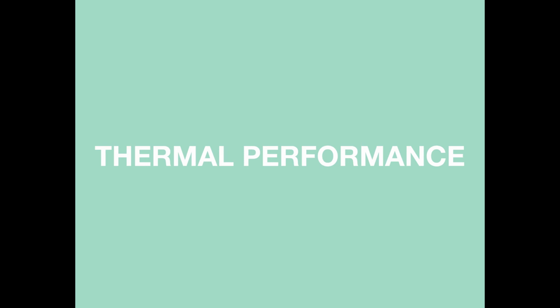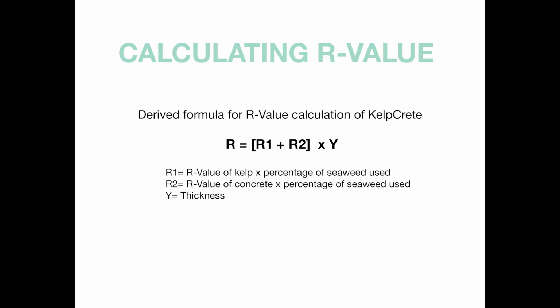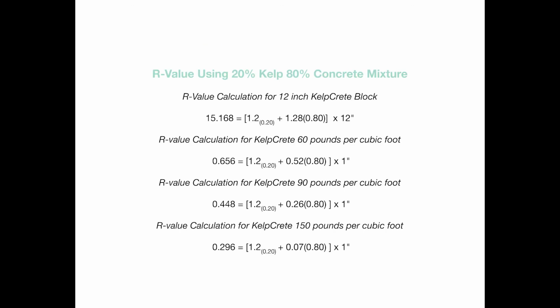Thermal performance. Thermal performance is the measurement of how well a material retains or dissipates heat and energy. In order to figure out how well our material performs, we needed to figure out the R value of Kelpcrete. This is the formula we derived to calculate the R value given a certain percentage of kelp additives. These are the results of our formula in action, using 20% kelp mixture. The R value increases compared to traditional concrete. This is the results of our formula using 30% kelp mixture. The R value increases even further compared to traditional concrete.